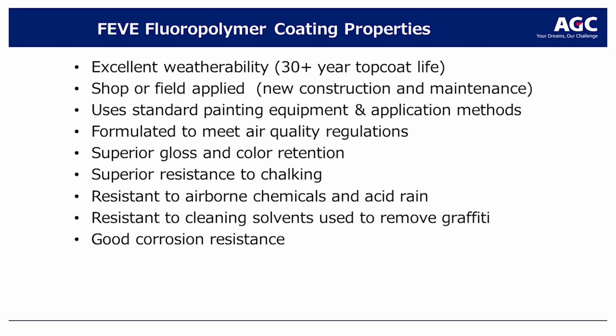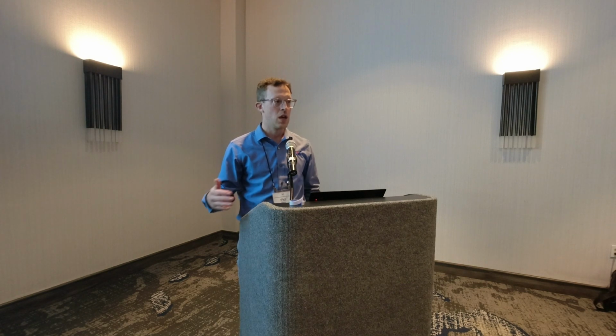So just to go through some of the properties, there's certainly a lot to be taken advantage of within this chemistry set, but you're looking at a coating that gets you 30 plus years. And we can confidently say that because we've seen that within the field, especially within Japan, where they've used these coatings, and that was the main reason they were invented.